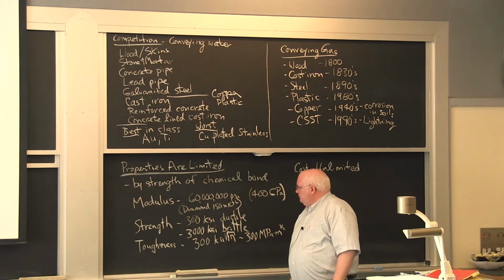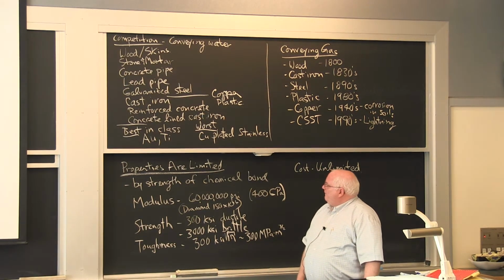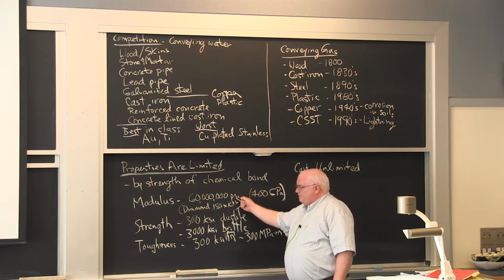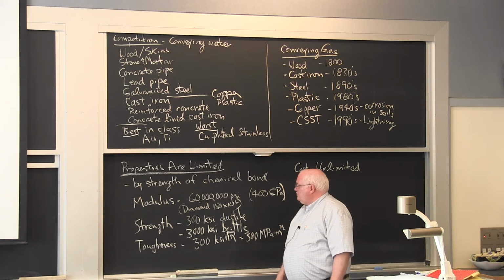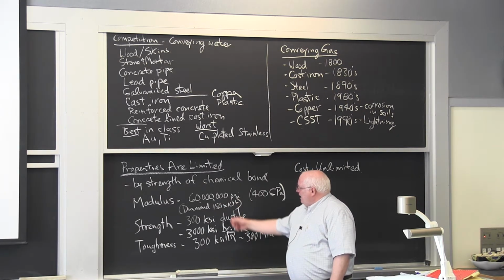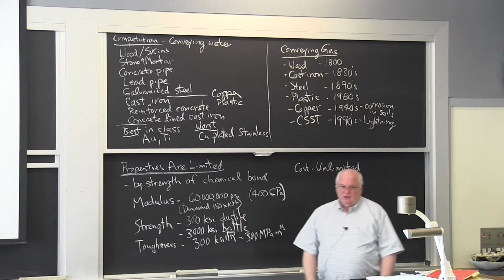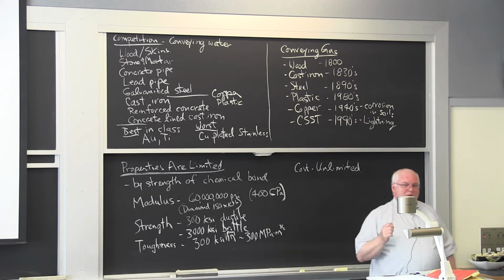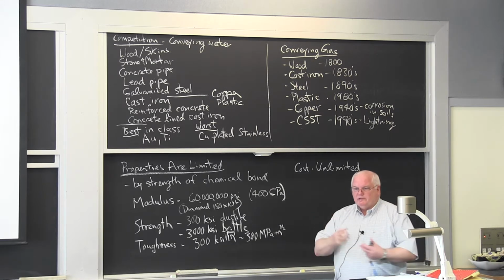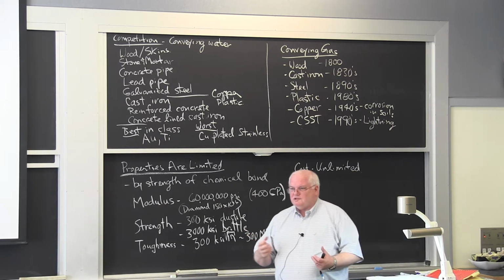And there's a limit to the strength of chemical bonds, about 3 electron volts per atom, which is like 400 kilojoules per mole. So the modulus of most things is no more. Steel's about 30 million, but molybdenum alloys and tungsten alloys are close to 60 million. They have double the modulus of steel. Diamond is actually 150 million, but the problem with diamond is it's very hard to get it in long lengths, big diameters and things like that as a structural material.